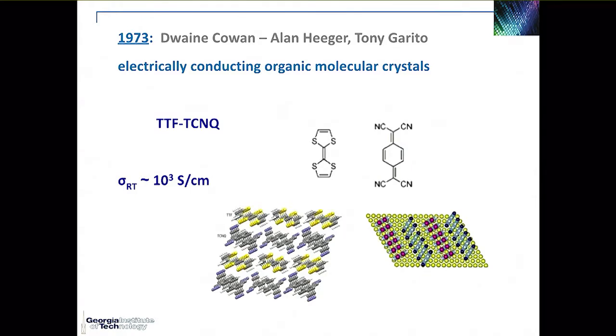The main point that led to that high electrical conductivity was the fact that it's a crystal with an electron donor, tetrathiafulvalene, TTF, and an electron acceptor, tetracyanoquinodimethane, TCNQ. While generally in those donor-acceptor molecular crystals you have alternating stacks of donors and acceptors, in this case you got segregated stacks of TTF and TCNQ molecules separated from one another, which allowed the holes to move along the TTF stacks and electrons along the TCNQ stacks, leading to that very high electrical conductivity.